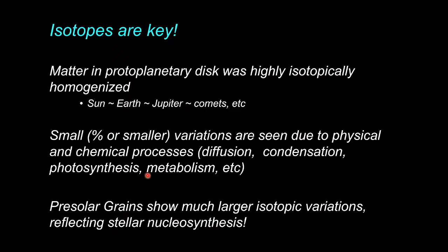So I showed you that the sapphire grain was 5 times higher in O-17 to 16. The whole range of oxygen 17 to 16 for material formed in the solar system is maybe plus or minus 5%. So if you go to a factor of 5, we have grains that are a factor of 30 times higher than the sun. It's pointing to nuclear reactions. That's the only thing in nature that can make such large variations, and where nuclear reactions happen is in stars. So that's how we know we have stellar material that we can study.